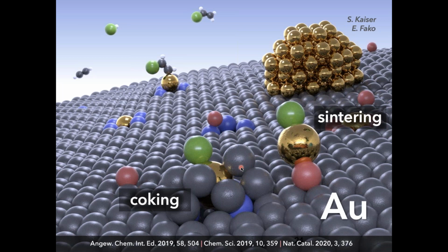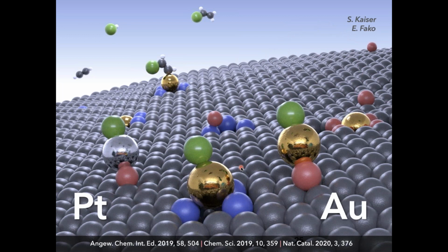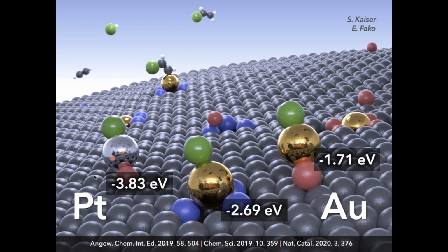which make this technology of less value. So what we thought is, instead of dealing with gold, we took platinum. And we know platinum does not require any nitrogen ligand because it will stabilize already very strongly on an oxygen site. So that's a platinum single atom. So it's a platinum adatom. So it already stabilizes with minus 3.83, much stronger than even gold on nitrogen-doped carbon. So we have the higher stability towards mobility with respect to the single gold on oxygen, but the advantage of not having nitrogen that could favor coking. So with this system, actually what you can get is a very stable behavior.